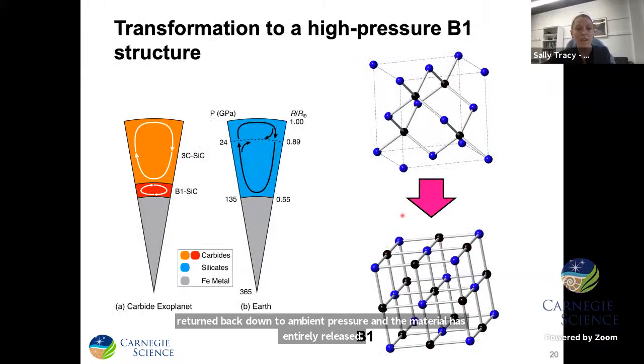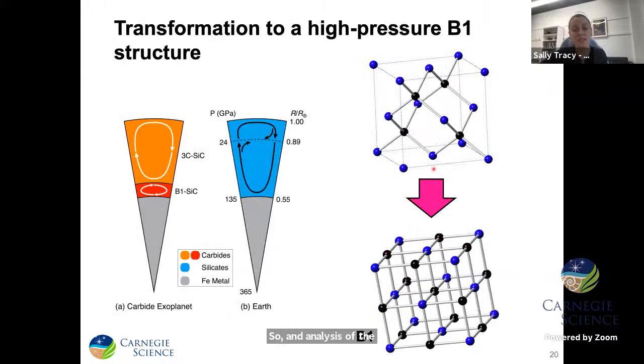So an analysis of this data reveals that similar to SiO2, silicon carbide undergoes a phase transformation from a 4-coordinated low pressure phase to a high pressure phase called a B1 structure, in which every silicon atom has 6 carbon neighbors and vice versa.